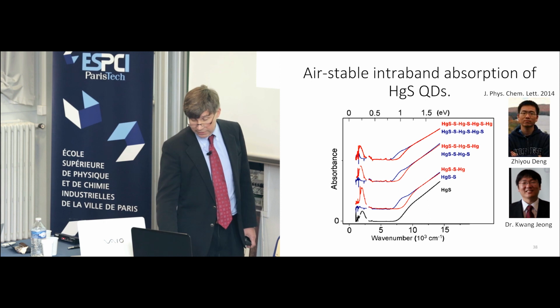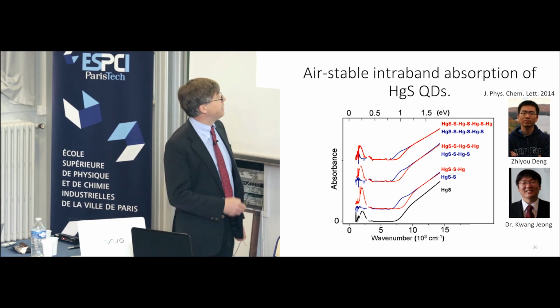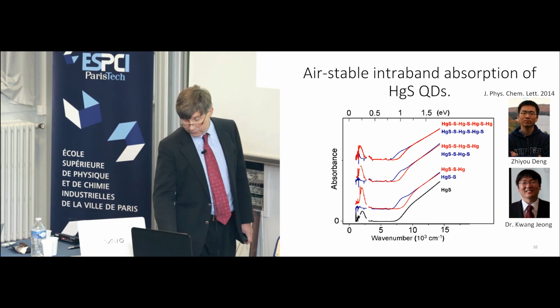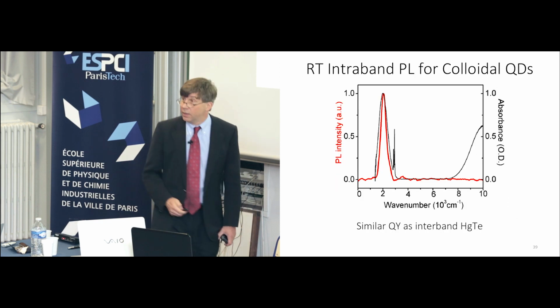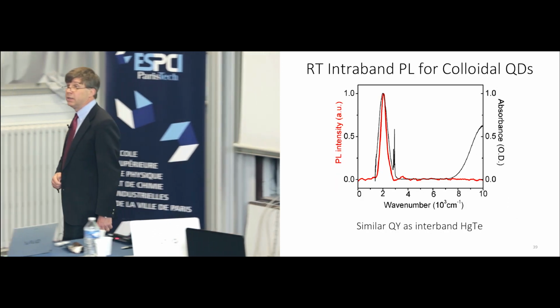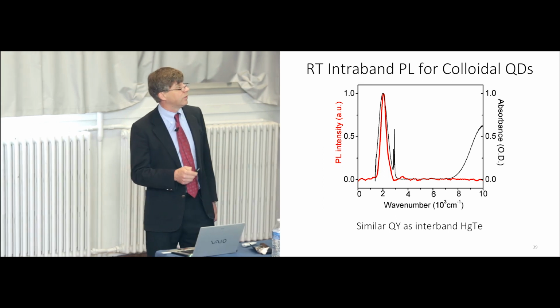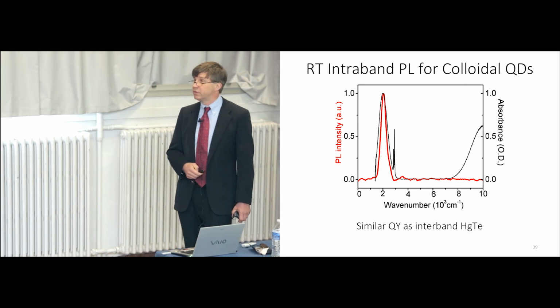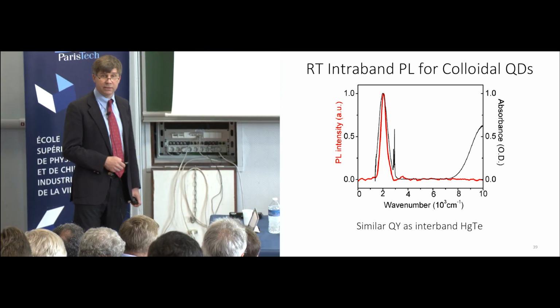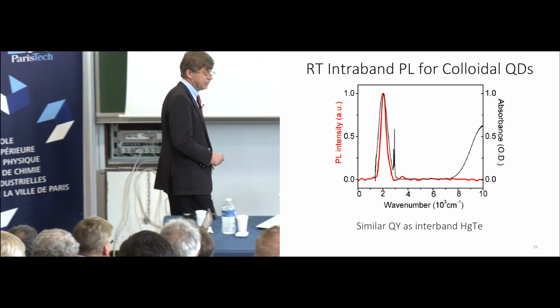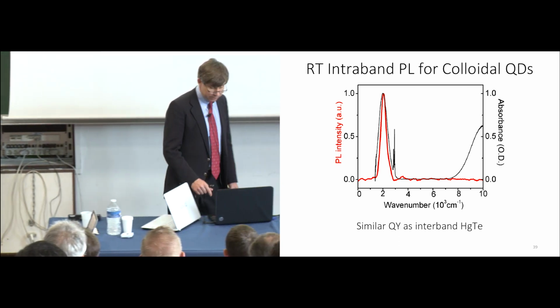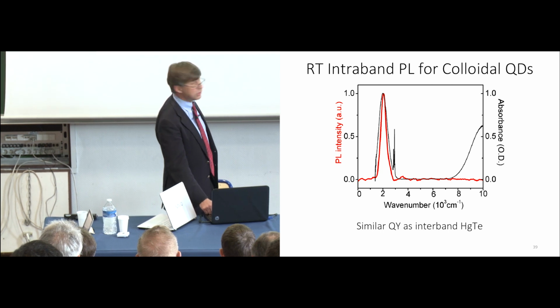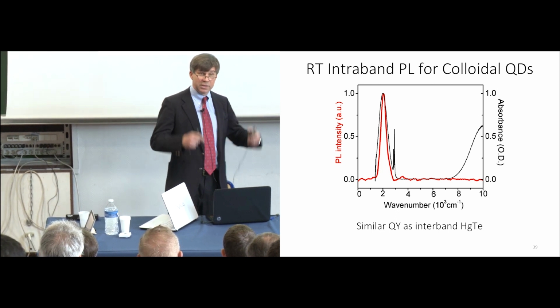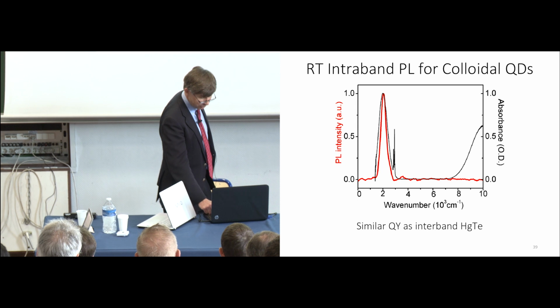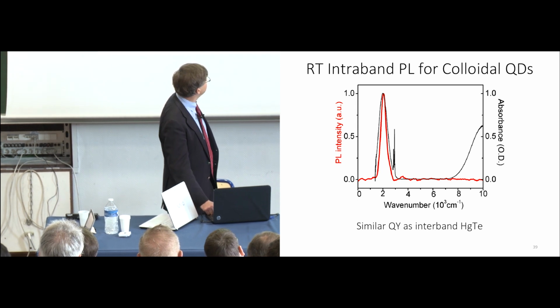So there is a system that is naturally doped, and if you control the doping, you get just 2 electrons in that lowest quantum state. It fluoresces. The intraband absorption leads to fluorescence, and it's just about the same quantum efficiency as mercury telluride interband emission. So that's the first case of intraband PL. It's very promising, of course. It tells us that the system is well behaved, that there's no states between the 1p and the 1s transition that would quench the luminescence more than it should.